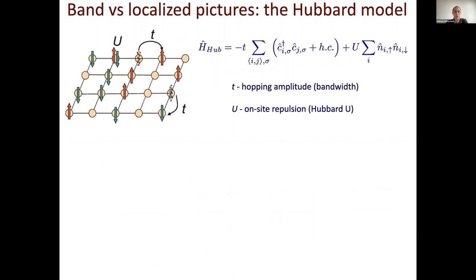Basically, we know that this is due to the fact that most of the approximations of the exchange correlation functional are based on the homogeneous electron gas, which of course favors a metallic ground state and over-delocalization of electrons, etc. So we want to use a model Hamiltonian, the Hubbard Hamiltonian, that is much better suited to capture also electronic correlation when the interaction between electrons becomes stronger.